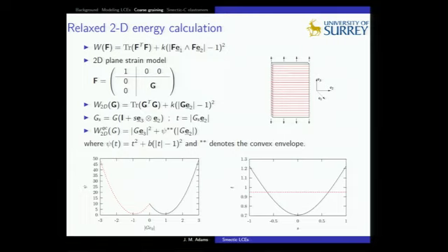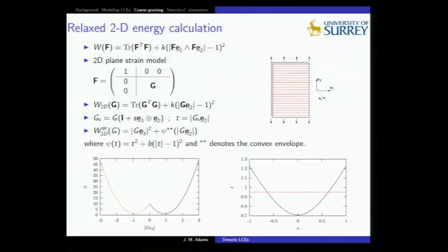So you'd like to choose the value of S in your deformation, the extra bit of shear, to change the value of GE2, which will change the value of psi to be in the minimum of your energy. That will just give you whatever the shear happens to be. And you're essentially solving this formula here for T. It's some sort of parabola, and you get two solutions, and they're your two deformations that you can substitute back into the energy.